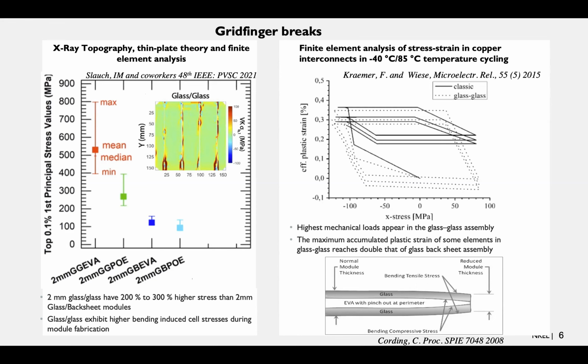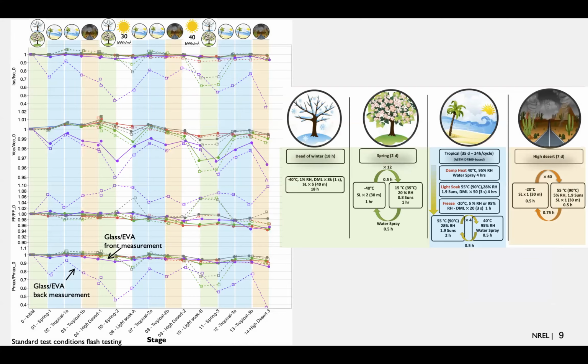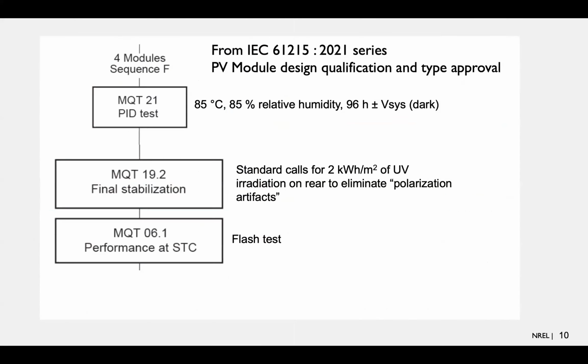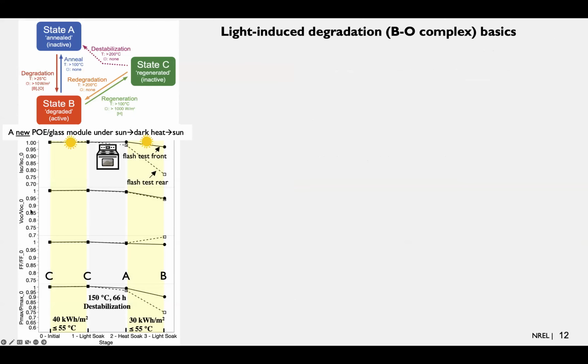A quick question: was this a P-type? What's the dopant of the P-type PERC, boron or gallium? Based simply on the age of the cells and the modules, it's boron. But did we go in with SIMS to measure it? No. But after discussions, just based on the time frame and the behavior, looking at a figure like this, this is classic boron-oxygen light induced degradation. So we're missing SIMS data. We did not measure that. Okay, that's a reasonable assumption, though.